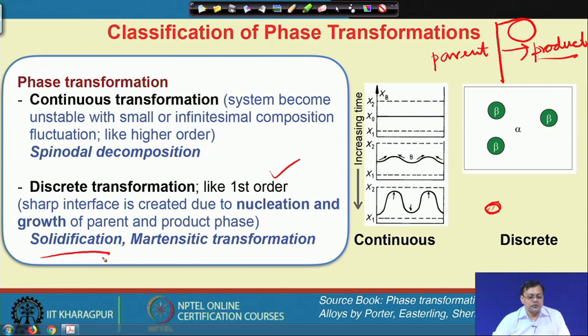The usual example of such discrete transformation is solidification. Here we already know that if we take a liquid and solid nuclei have to appear, first a particular cluster will appear, and if they have a greater size than the critical size of a nucleus, then they will be stabilized, and there should be a net decrease of the free energy of the system, and we need some activation barrier for such a case. Also, a Martensitic transformation is a first order transformation. Here the transformation goes through a nucleation of the Martensite plate and its growth in the austenite phase. So, this is a discrete transformation.